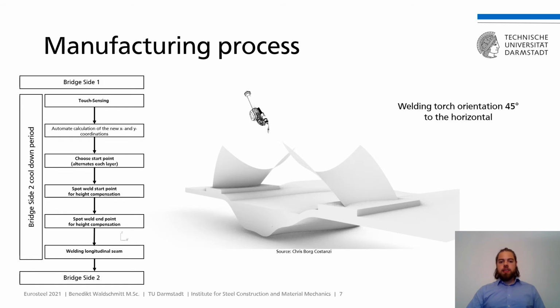A spot weld at the start and end point before the start of the continuous layer application compensates for the local height loss and at the same time prevents the wire tip from missing the last applied layer. Subsequently, the continuous material application alternates in the welding direction for each welding layer. For a constant travel and wire feed speed, the seam geometry is higher at the beginning and flatter at the end. To avoid propagation of the height difference, both properties are cancelled out by the alternating welding direction.